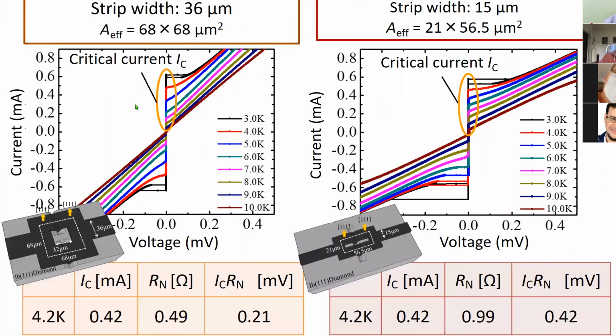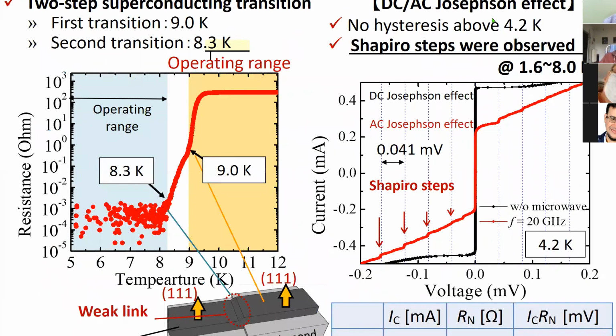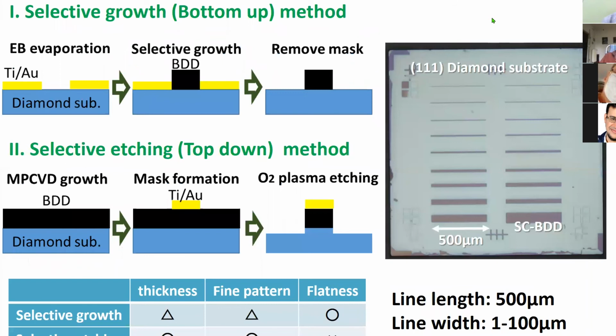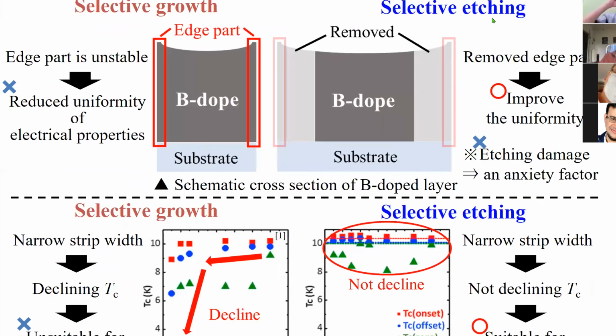Oh yes, 30 to 50 microns, but now we want to approach the micron or submicron region. To get this, we should make a very narrow boron doped layer, and we use selective growth or etching.